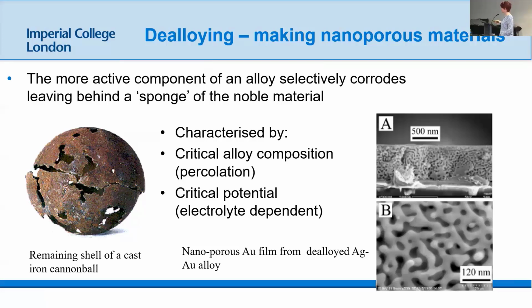And it's characterized by these critical parameters: an alloy composition, which is a percolation type threshold, and a critical potential, which is electrolyte dependent.